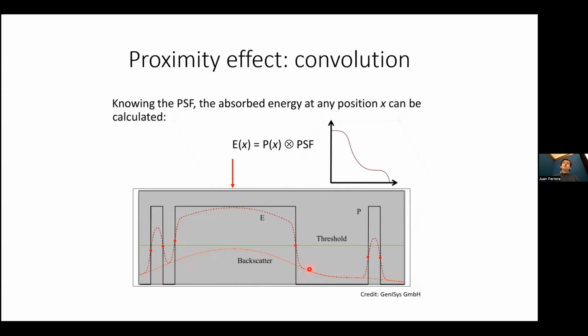Usually when you have a convolution problem, you can invert it, but in this case, energy can only be deposited, it can't be taken away. So once you deposit energy in these areas where you don't want it, you can't take it away. So the only thing that you can do is change the dose, for example, this line should get a larger dose, and then hopefully that will equalize the threshold with respect to these red dots, which is where you want the pattern to be resolved.